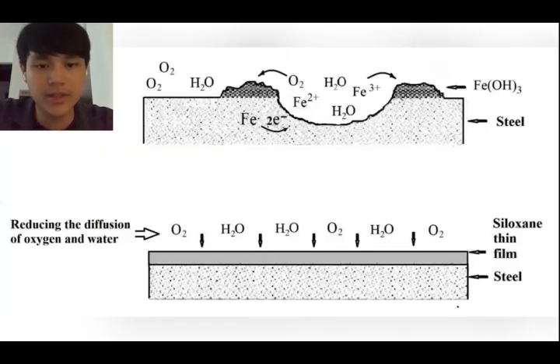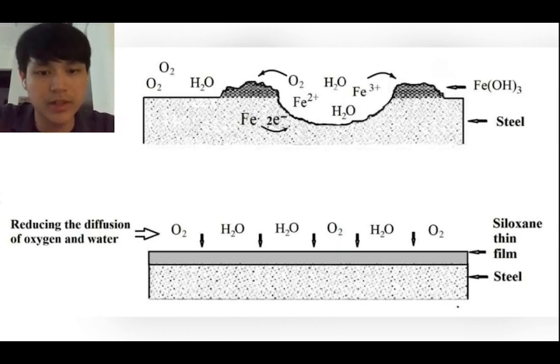Now, these are the key reactions and mechanisms of how organosilanes improve the most important property, which is corrosion protection. When a polymer coating is applied on an organosilane modified surface, the interpenetrating diffusion occurs, which means the anodic dissolution will be decreased, causing the corrosion rate to also decrease. One more thing to note is that negative charge tends to prevent the adsorption of corrosive chloride. Thus, ionic sulfur groups are introduced with imidodiacetate groups into the organic radical of the silane molecule to produce the siloxane layer, and this layer reduces the absorption of water.